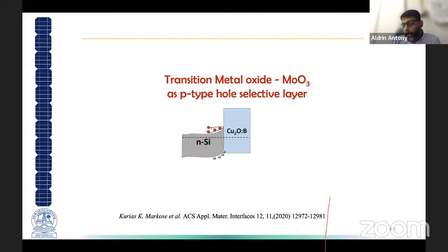Okay, so now we move on to another material that we call MoO3, that is a metal oxide. It's a transition metal oxide, and that also can be used as a very good hole selective layer with the crystalline silicon. Here, slightly different than the earlier one. In the earlier one, copper boron oxide was itself a P-type material, which gives a very good band alignment with the silicon.